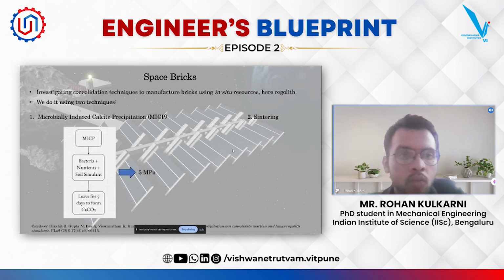So in MICP, we have some bacteria, we give some nutrients to the bacteria, and we then put this into a soil. Then after 5 days, this bacteria secretes calcium carbonate, and this calcium carbonate covers the entire surface of the loose soil and forms the consolidation. So we have reached a strength of 5 megapascals with just by using a bacteria, which is almost comparable with the strength that we have on our bricks.